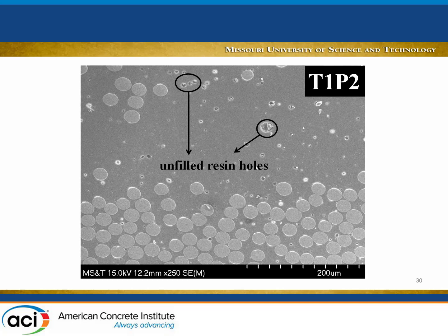Here is just another sample of the SEM specimens that we get from the tank. So this is tank 1, the low temperature, period 2, that's about 6 months. And we don't really see much. We have some holes here in the resin that we believe are just from manufacturing.